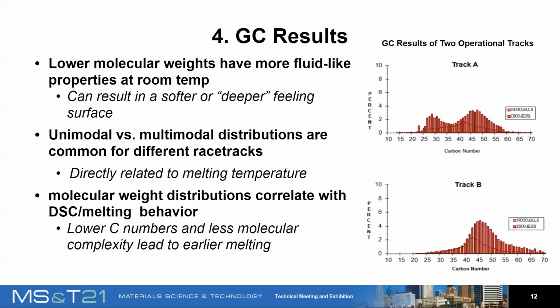Now, lower complexities do lead to lower energy requirements to break the molecular interactions within wax, leading to a softer, spongier wax. The mass percent distributions can also be determined by the GC and can generally correlate with some of the thermal effects seen in the DSC. In the two graphs shown, the lower graph shows a standard unimodal weight distribution centered around C45, while the upper graph exhibits a bimodal weight distribution, which indicates additional compounds were added to the original wax. These graphs correlate to their melting behavior and can also be seen in the FTIR.